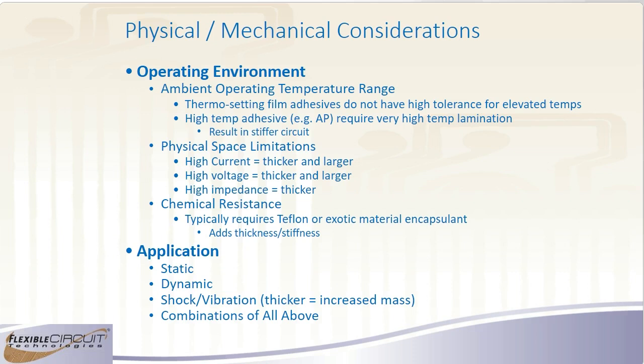then you're going to have a pretty in-depth discussion with some designers and a manufacturer to figure out how to do that, because that's going to be a tough go. I would say that if you needed a dynamic application, you're almost going to have to go with a shielding film in order to get it thin enough to be able to operate dynamically long-term. But for static application, figure 20-to-1 circuit thickness to bend ratios. And you talked about having thicker traces, so that probably would be a good guideline.